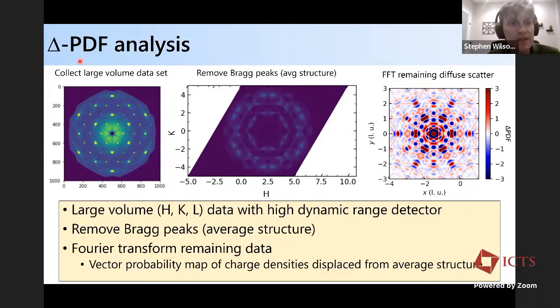To do that, we did what's known as delta PDF analysis. It's basically taking a large volume of X-ray diffuse scattering data and punching out the Bragg peaks, which removes the average structure. Then you can Fourier transform that into real space and look at what's effectively a vector probability map of charge densities which are displaced from the average structure.